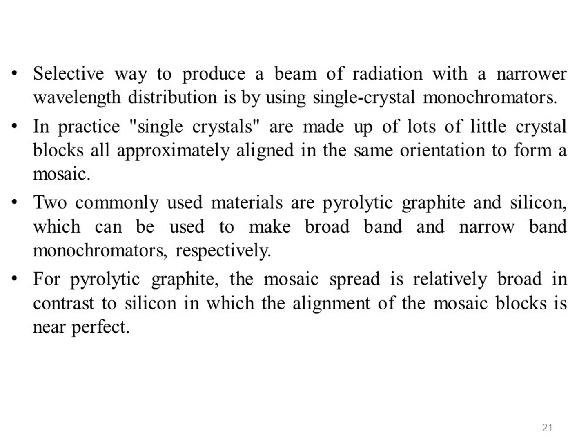In practice, single crystals are made up of a lot of little crystal blocks, all approximately aligned in the same orientation to form a mosaic. The distribution of the alignment of the blocks determines the so-called mosaic spread of the crystal. Two types of monochromator may be distinguished based on the difference in the mosaic spread of the crystal. Two commonly used materials are pyrolytic graphite and silicon, which can be used to make broadband and narrowband, meaning delta lambda over lambda, monochromators respectively. For pyrolytic graphite, the mosaic spread is relatively broad in contrast to silicon, in which the alignment of the mosaic blocks is near perfect.